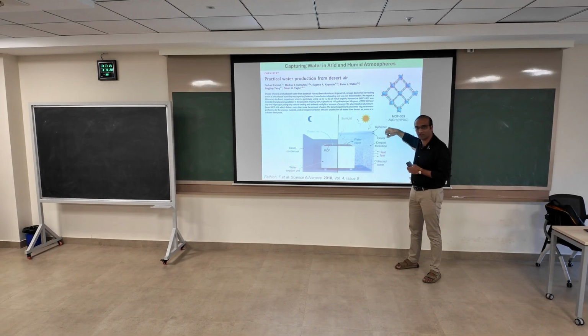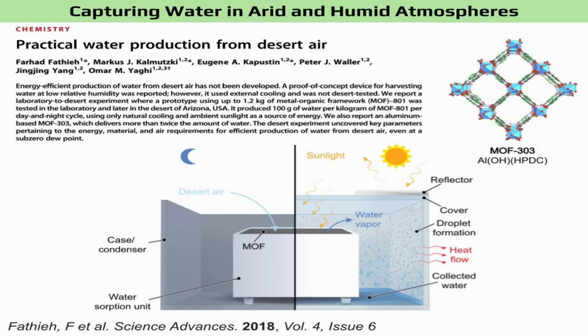Okay, it's again made from very cost-effective materials. You have aluminum as a salt, and then you have these compounds. Essentially, during the night when the humidity is very high, you keep this thing open, and you have MOF loaded inside this filter. You keep the slide open, and the desert air will keep circling into this chamber. Whatever MOF is there is very adsorptive. It takes all the water in from the air, and the air goes back out.